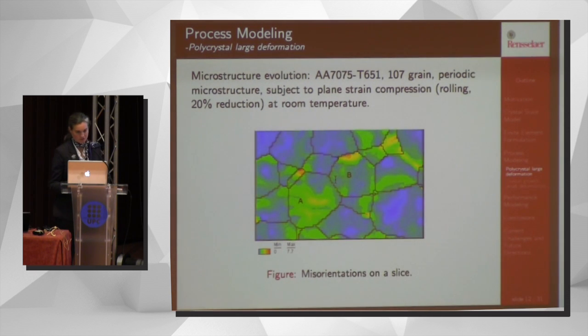And we can look at the misorientation, for example, on a slice through that polycrystal at some location. Here we're not considering misorientations across a grain boundary, only within the grain. So here we see a gradient of orientations occurring near a grain boundary, which is not surprising. We also see interior misorientations. Now, our simulation probably smears that out some. We don't have experiments that go along with this, but I think in practice you would see this to be more focused, not as diffuse.